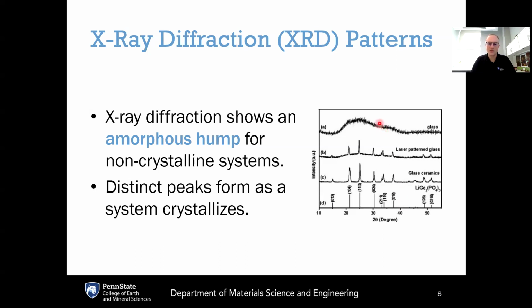On the other hand, at the other extreme, if you have a glassy sample, what you will get from an X-ray diffraction pattern looks like what's shown on the top here, where you have kind of this hump, and this hump is generally known as an amorphous hump, although more properly, it should probably be known as a non-crystalline hump because the same type of hump exists in both glassy materials and amorphous solids. It exists in both because both types of materials are non-crystalline. Both glasses and amorphous solids have non-crystalline structures, and that lack of crystallinity means that instead of having all these sharp peaks, you just kind of have this hump with a bunch of noise around the hump.